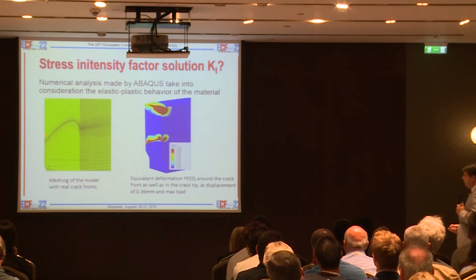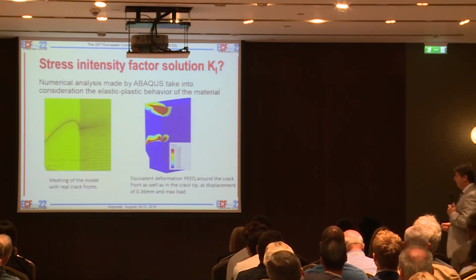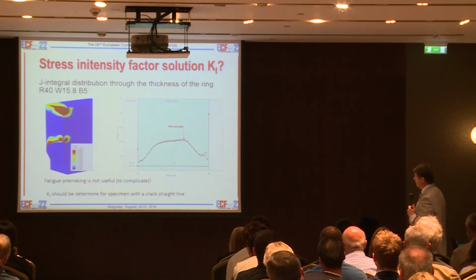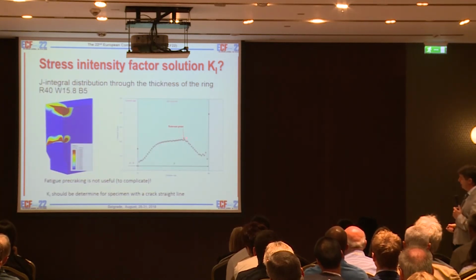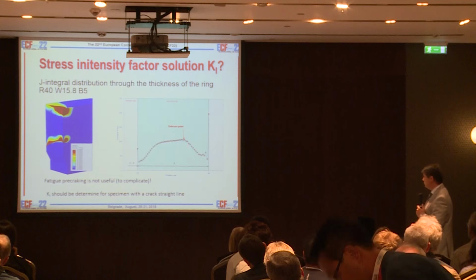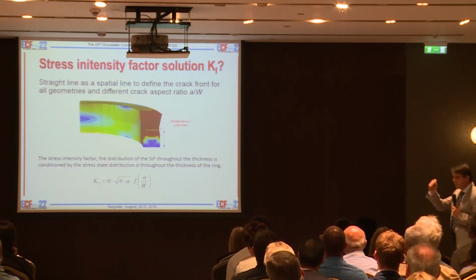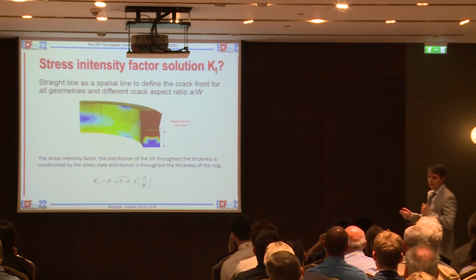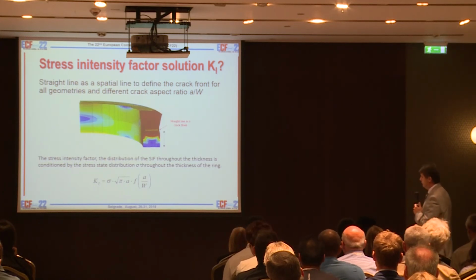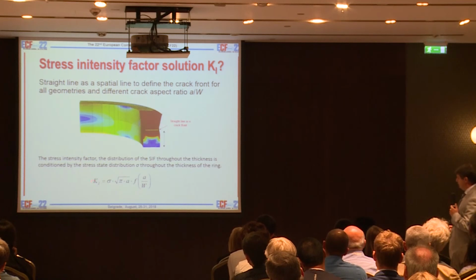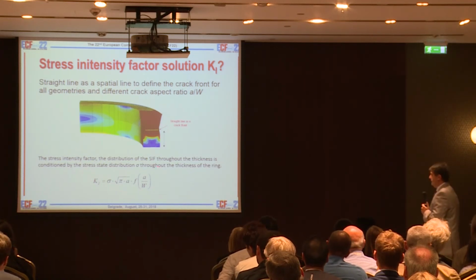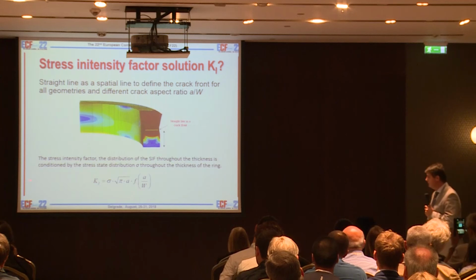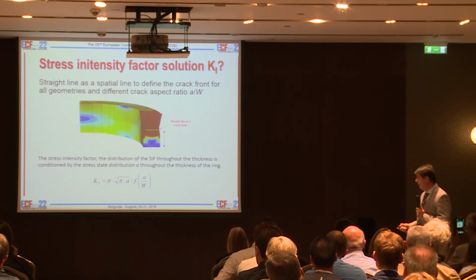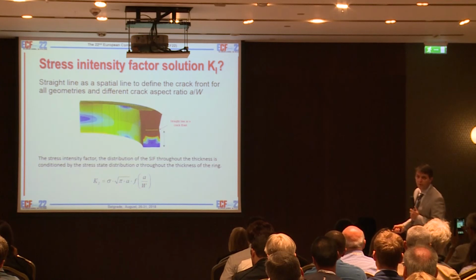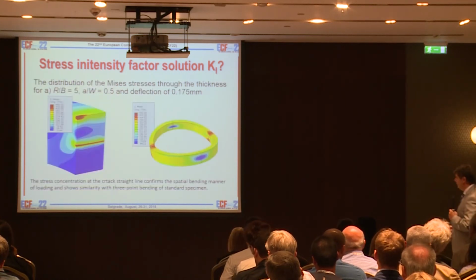And then we also compare with what we have on the specimen with a crack front. Here we use a solution like the highest stress intensity factor which we get at the crack initiation point. So it is only used for the beginning of the line, as crack initiation is a relative fracture toughness parameter. So here is the formula which is used for stress intensity factor for the three-point bending specimen, and we use a similar formula here, but we only want to change the shape function and compare this shape function in both cases.